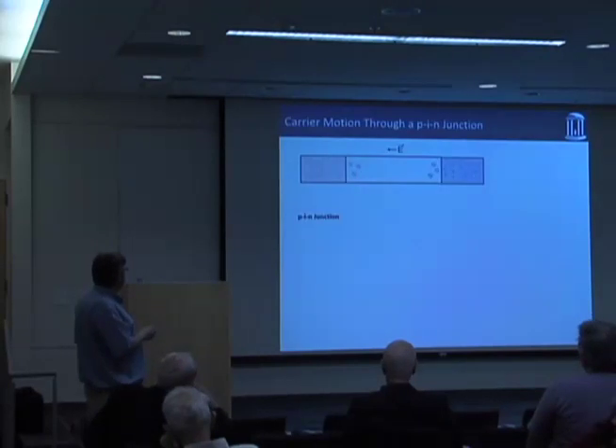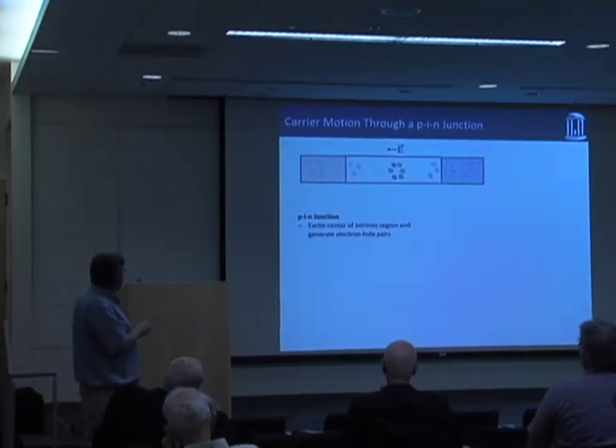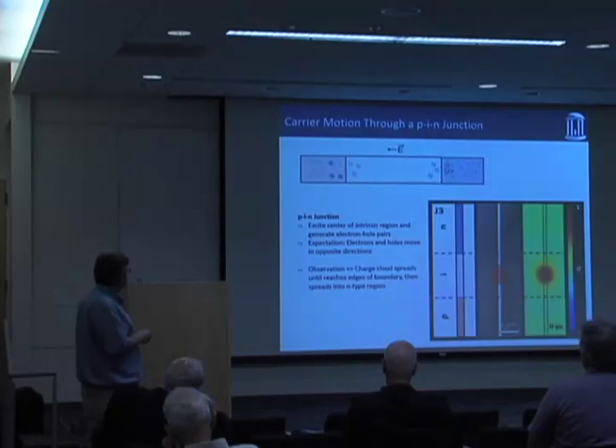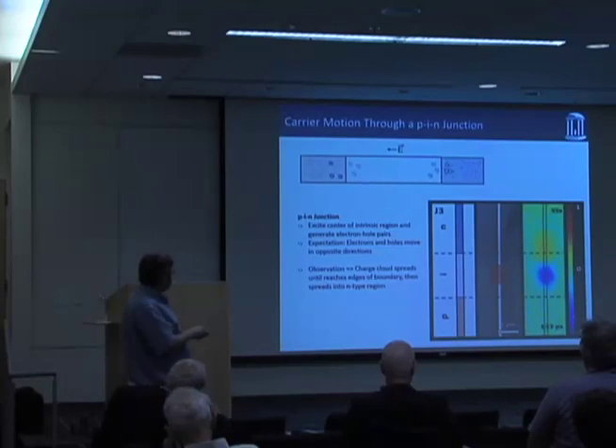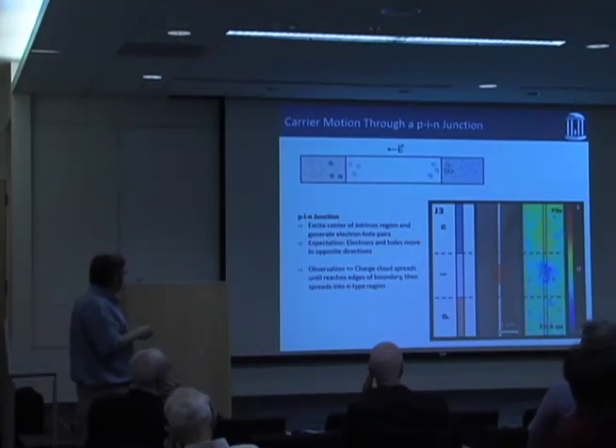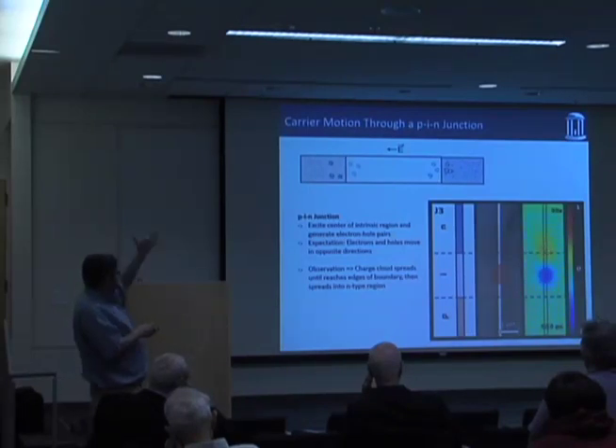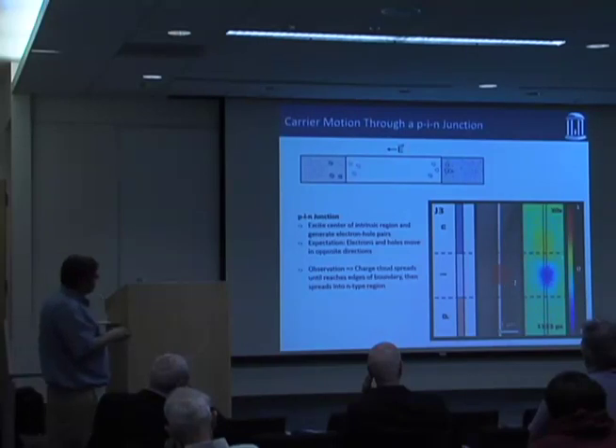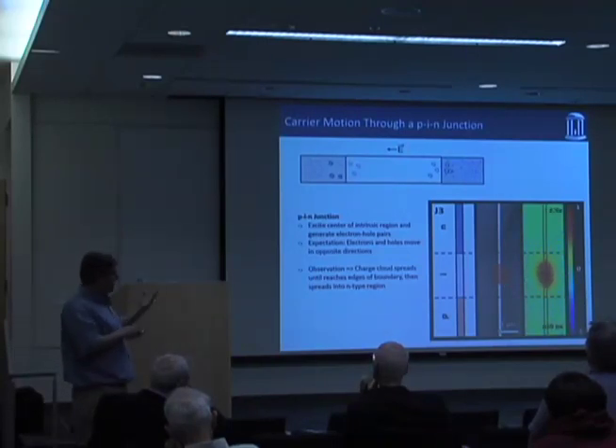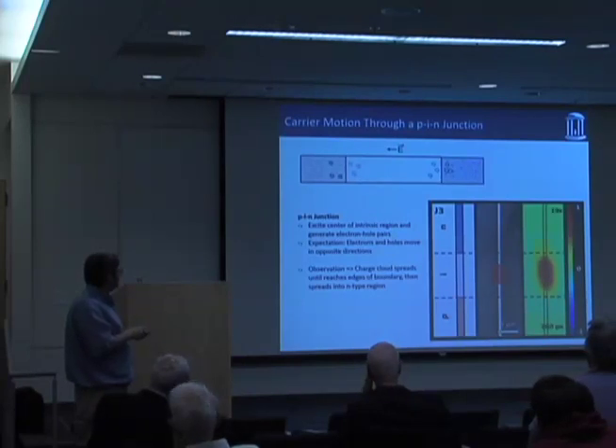Okay, so anyway, what we did was we took this junction, we excite it in the middle of the undoped region, and then we look to see whether we see charge separation. This is one of those spatially separated images where the pump is always here in the middle of the intrinsic region, and then we're raster scanning the probe over the pump at a series of different time delays. What you see is initially this charge cloud expands. It reaches the edges of the intrinsic region, and then all of a sudden a piece of it peels off and heads north. And then you're left with this long-lived trap signal that we can't seem to get away from, appearing at longer times.